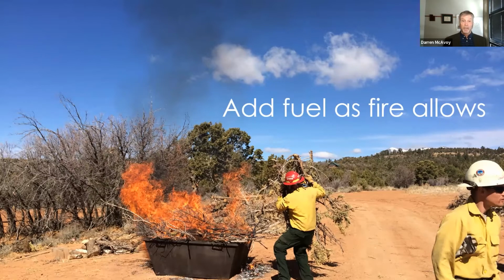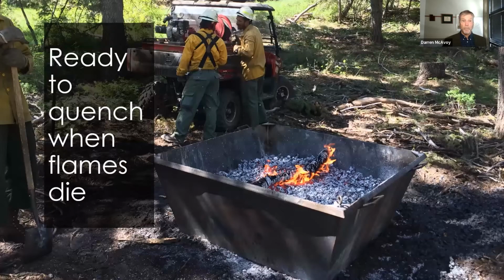But in super dry conditions, you can consume perhaps 10 times the volume of the kiln at once. And in super wet conditions, it might be closer to 4 times the volume of the kiln. And so we're looking for a point when the kiln is close to full of coals, or you're done with the fuel surrounding the kiln, and the flames drop from flaming combustion to a glowing combustion.